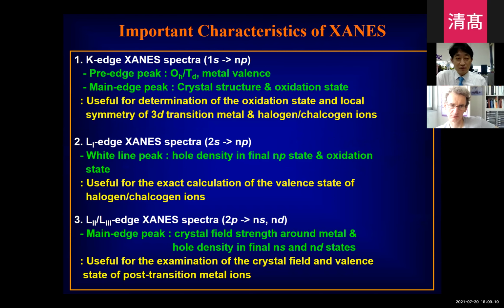I love XANES because from the spectral features of XANES, we can get many valuable pieces of information. For instance, in a K-edge XANES spectrum, there are pre-edge peaks and the main edge peaks. From the pre-edge peaks, we can get valuable information about the local structure of the metal ion, octahedral or tetrahedral. As you know, the intensity of the pre-edge peak is proportional to the structural distortion from the centrosymmetric octahedral symmetry. Also, from the position of the pre-edge peak, we can determine the metal valence. Also, from the main edge peak, from the variation of peak intensity and position, we can get information about the crystal structure, the bonding nature and the oxidation state.